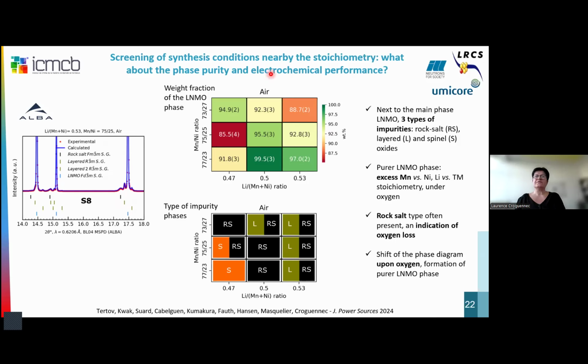So this graph gives an evolution according to the composition in manganese and nickel: the stoichiometric, the deficiency in manganese, the excess in manganese, and at the bottom you have the stoichiometry in lithium versus transition metals. You can see that the greener it is, the purer the LNMO phase is. Here we are close to purity, and here, with oxygen, we have full purity of these materials.